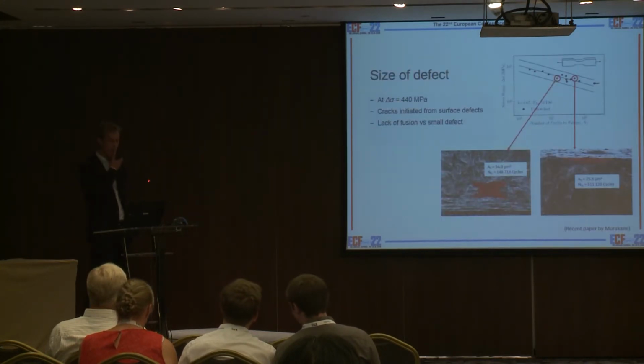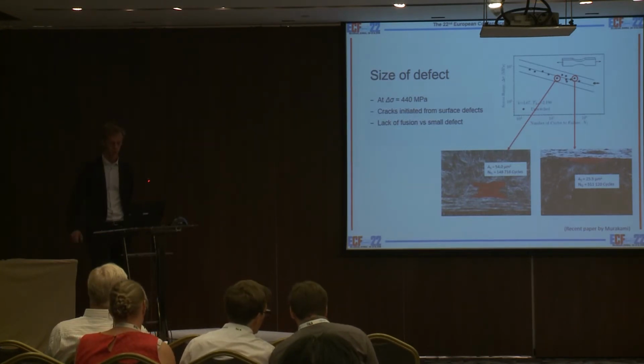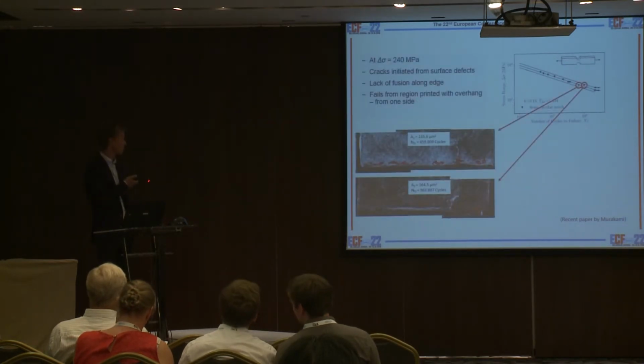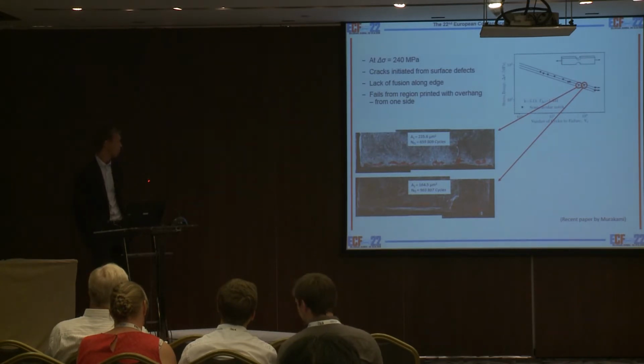And there was a larger scatter in the unnotched data. So we looked to the surface defects and found a kind of correlation. There is a larger surface defect for the sample failing earlier than for the sample having a longer life. And also this is the case for the semicircular one. There is a kind of surface defect along the whole edge, and also a correlation between the surface area and the fatigue life.